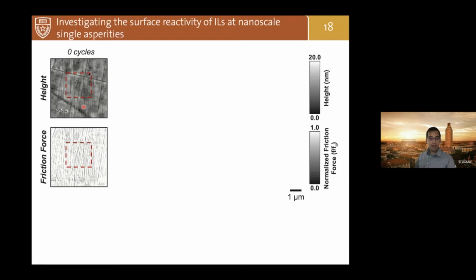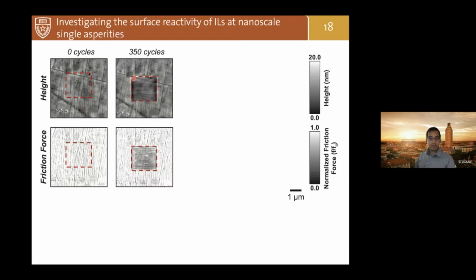So if we slide for 350 cycles, the part in the middle, and then we zoom out and we take a new image, that's the second image that you see here. What you see is an area which is slightly darker, meaning that it has slightly lower height. In other words, we are removing material. At the same time, we see a darker region in the friction force, meaning that we are decreasing the friction